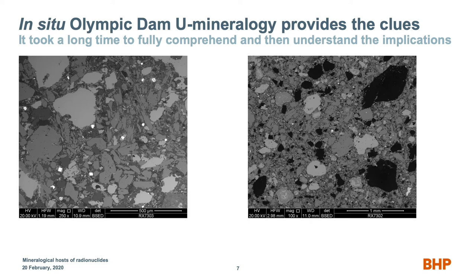So over here, backscattered electron image. Again, we're going to look for bright spots, and this has a scale of 500 microns, and that's a 1 millimeter one. Very typical kind of ores. These big chunks like that are sulfides. These little bit grayer ones are hematite, and these little tiny bright spots are uranium minerals around.